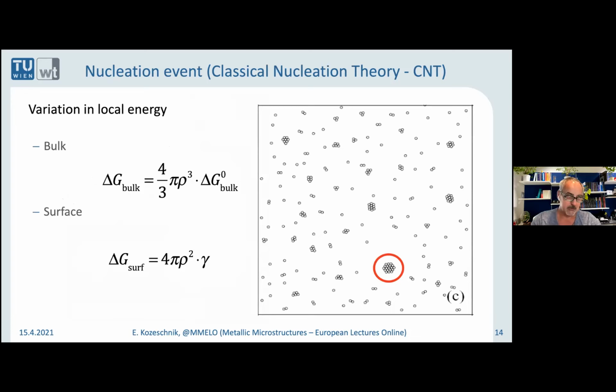When you look at some kind of, let's say, solution, then you will recognize that the monomers or the molecules that will form the second phase appear either as a single molecule or together with like dimers or trimers and so on. And eventually, when you have a supersaturated solution, there might come up a nucleus which is large enough to become stable. And the main idea of classical nucleation theory is now to consider this nucleation event in terms of the local energy, the changes in the bulk energy, the volume energy, and the changes in the energy related to the creation of new surface. So we have a term which involves the volume free energy change due to the change of phase multiplied with the volume of the nucleus, and the same with the specific interface energy multiplied with surface area.